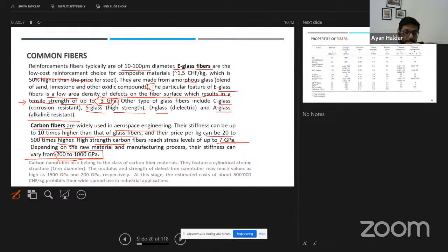Now, carbon nanotubes also belong to the class of carbon fiber materials. They feature cylindrical atomic structures. In recent years we have also developed fibers in the nano form, in the form of nanotubes. They are called carbon nanotubes, you might have heard of CNTs, right? These are very thin, 1 nanometer diameter structures. They are almost defect free, and they can offer a very high elastic modulus, about 1500 gigapascal, and even a strength that can reach 200 gigapascal, which is incredible.